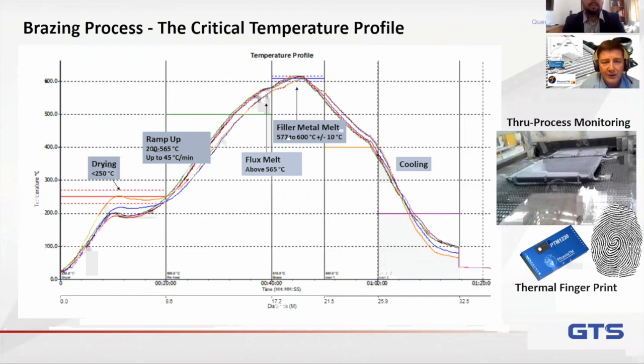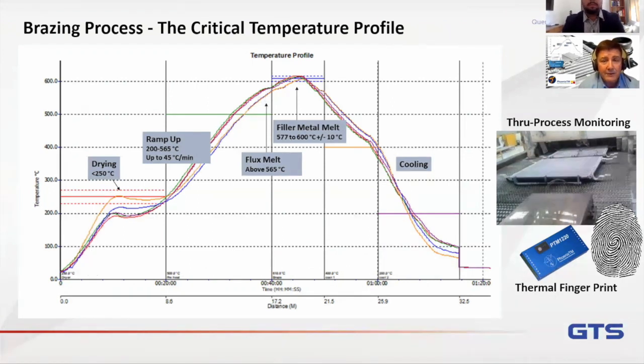Now, you'll notice that there are multiple traces of different colors, and that's because different thermocouples were attached to the product as it was measured through the furnace. A profile like this can be measured, as has been done traditionally, by a technique that we call trailing thermocouples. Very long thermocouples are fed through the furnace with the product, and an external data logger is then used to record the profile. Although that is useful, it can cause potential problems from a safety standpoint. Obviously, putting a thermocouple through a furnace and hand feeding it can be very, very dangerous.